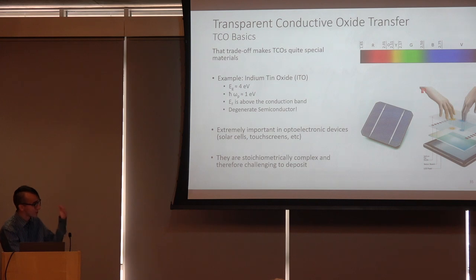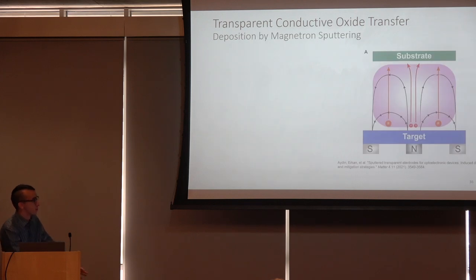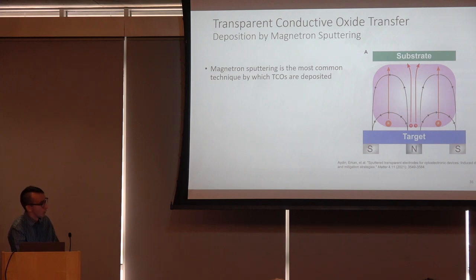Very important. However, these materials are stoichiometrically complex and therefore challenging to deposit. The typical approach to depositing these materials is via a process known as magnetron sputtering, whereby you take some gas particles such as argon and you energize them into a plasma. That plasma is then made to strike your target, which would be your puck of ITO in this case. And then that striking plasma causes atoms to be ejected from your puck and then deposited onto your substrate.